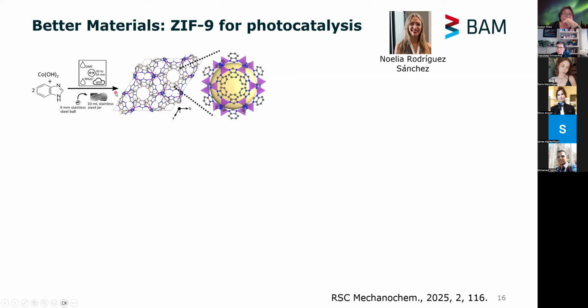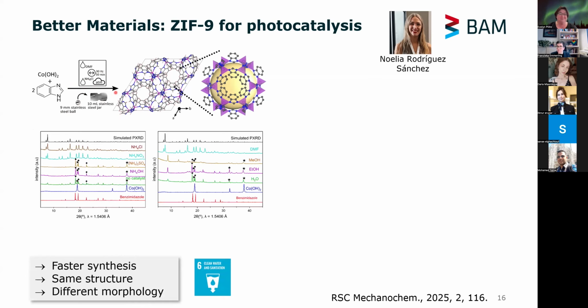It takes about 50 minutes, but is sometimes a bit of a process where you also look for highly crystalline materials. Just to make sure that it's not always an easy process, you can see there were several tries necessary to find the best recipe. So sodium chloride is the best additive in that case. And we are also not totally solventless. Sometimes there is a really minimal amount of solvent still necessary to make these reactions run to completeness.